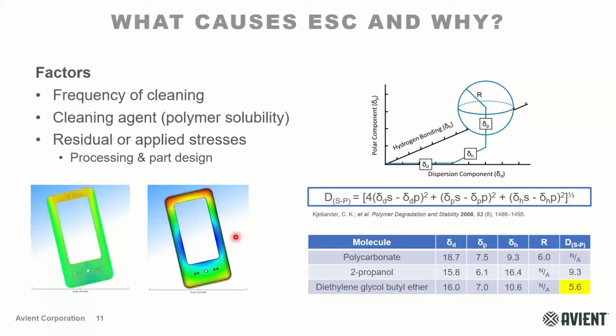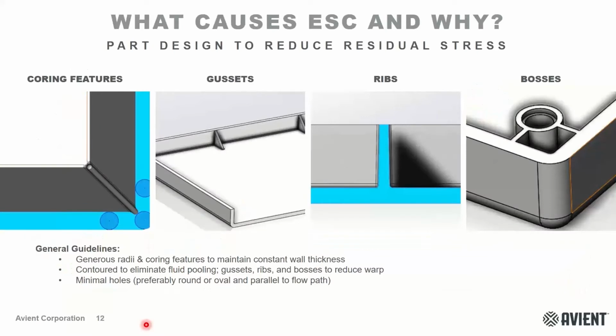The image next to this is an image of the mold shrink, so the red being higher shrink and the blue being lower shrink. And so a lot of times where you see the higher levels of shrink, there's commonly some residual stresses associated with those as well, mostly because the chains are being frozen and the stresses are being frozen into the part. So what can you do from a part design in order to try and help reduce residual stress?